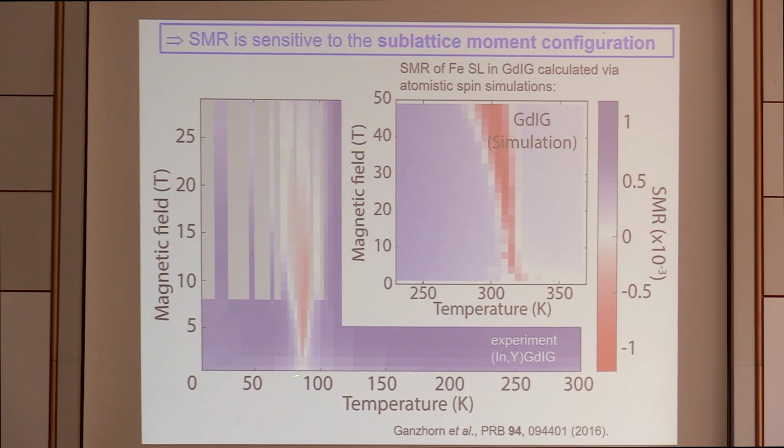Whereas in our samples, we introduced gadolinium, indium and yttrium, because it is known in the literature that you can shift the compensation temperature down below room temperature. We thought that would be a smart move because that would allow us experimentally to access this transition temperature very easily. In hindsight, after doing many experiments with these samples, that might not have been so smart, because comparing to calculations always comes with the caveat that we look at a material which has a different compensation temperature than the pure compound would have. But other than that, if you just renormalize the temperature, the behavior should be very similar.